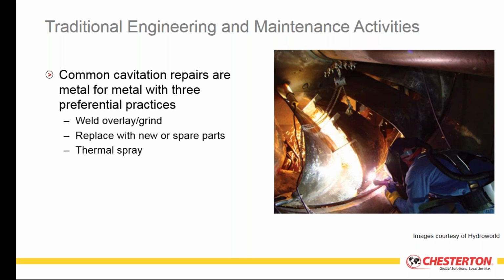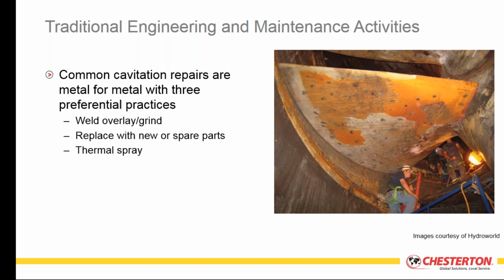But as far as the actual process itself, if it's done properly and effectively, it can be quite beneficial. If it's done ineffectively or improperly, in other words they do not provide the proper pre-treating or post-treating of the steel, or don't use the proper weld materials or welding techniques, or they're unable to grind everything smooth and flush again, they can actually accelerate and make the problem more difficult and more progressive. You can see some of these weld areas and grind areas are quite significant, so there's going to have to be a significant amount of post-treating after the welding as well as pre-treating.